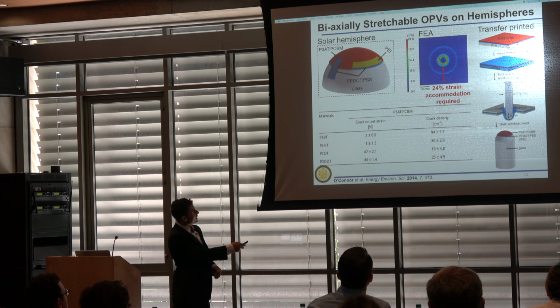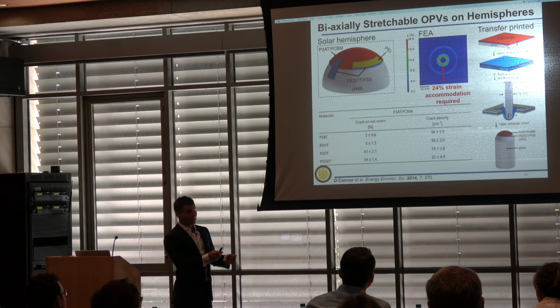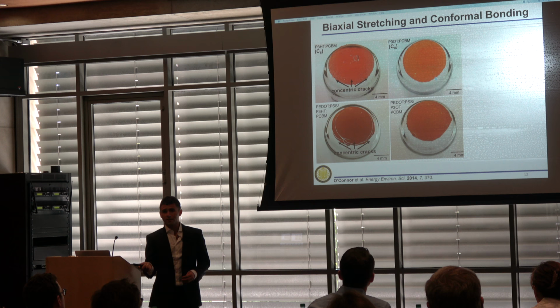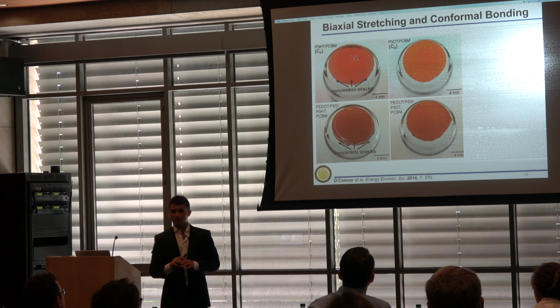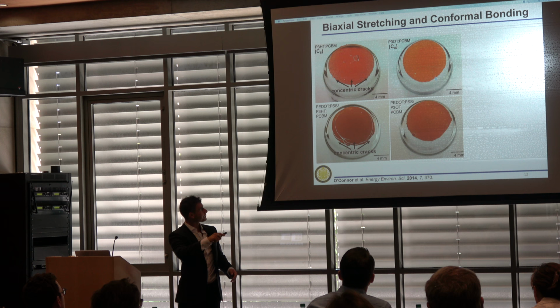our previous results had shown that at 3%, an unannealed thin film of C6 would crack, and at 47%, the composite of C8 would crack. So what we found was, as we see, these concentric cracks in the C6 composite, and C8 is a contiguous film, and then we made devices out of this as well. You see this catastrophic device cracking in C6, and C8 remains a fully intact solar cell.